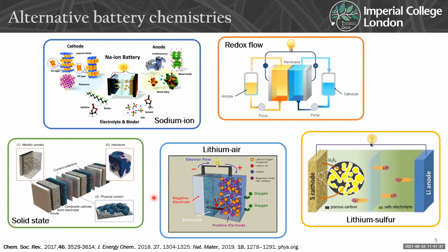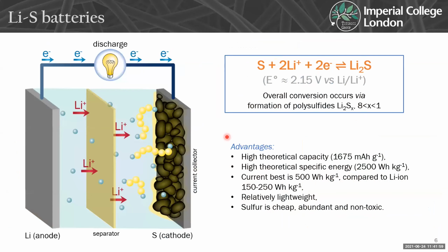Different options for that are solid state batteries, so replacing the electrolyte with a solid state electrolyte, or replacing one of the electrodes with air, so in lithium air batteries, or as I'm going to talk about today, lithium sulfur batteries. A lithium sulfur battery doesn't work in quite the same way as a traditional lithium ion battery. At the anode side, you've got the lithium metal, and on the cathode side, you've got the sulfur. The overall redox reaction in the cell is that sulfur converts to lithium sulfide, and that typically happens at a voltage of around 2.15 volts. But it's not a straightforward conversion. It goes through the formation of a whole series of polysulfides, which I will discuss later on.